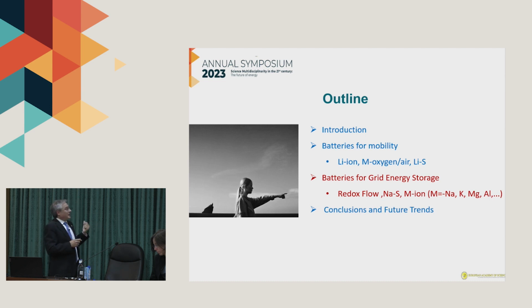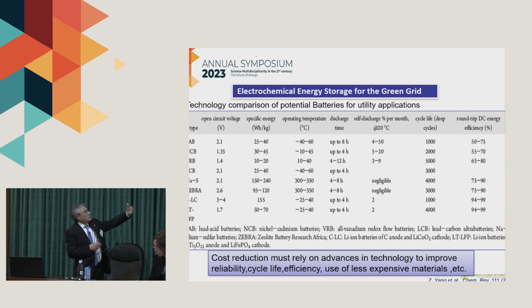Batteries for grid energy storage. In this case, we are moving to redox flow batteries and sodium sulfur batteries. We have here a table with a technology comparison of different batteries. The first ones have lead, nickel, cadmium, vanadium, and we know that these materials are not interesting to be commercialized. The sodium sulfur and Zebra have very good energy density, very good efficiency, and a good cycle life. The problem with these batteries is that they work at 300 to 350 degrees C, a high temperature.